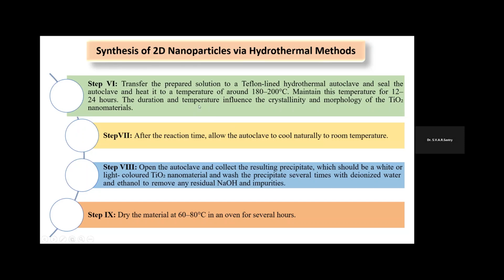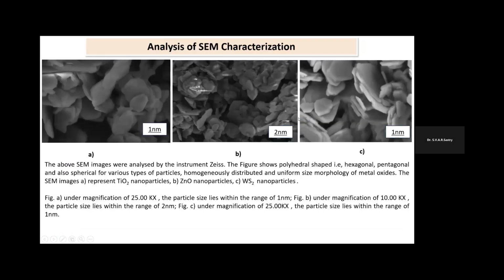So here the duration of time and the temperature influence the crystallinity and the morphology of the TiO2 nanoparticles. If you do analysis using SEM, the SEM instrument we used was made by Zeiss, and we saw that polyhedral shapes, like hexagonal and pentagonal, and also spherical shapes were observed in the nanoparticles formed, and they were homogeneously distributed with uniform size and morphology, especially for metal oxides. These SEM images represent TiO2 nanoparticles.